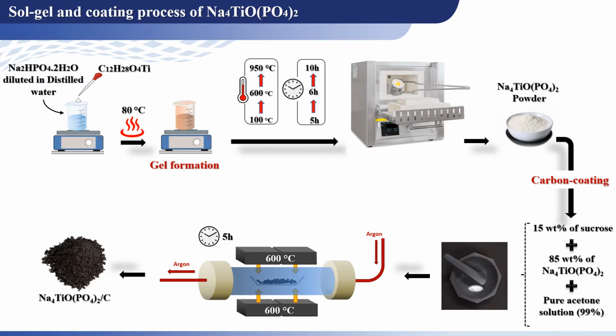As we all know, phosphate-based materials have poor electronic conductivity, so for that we proceeded to a carbon coating process to enhance the electronic conductivity. Our composite material was prepared by mixing 85% of the resultant powder and 15% of sucrose using pure acetone as solvent. The mixture was calcined at 600 degrees for 5 hours under an argon flow, and by the end we have obtained the black powder of the composite material.